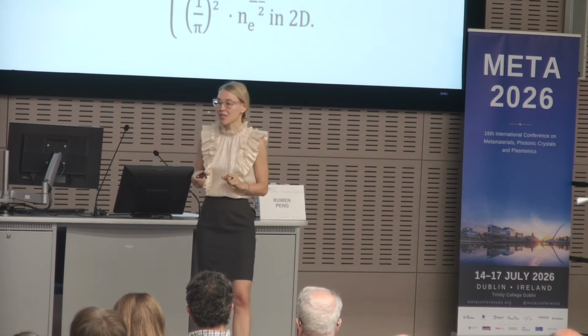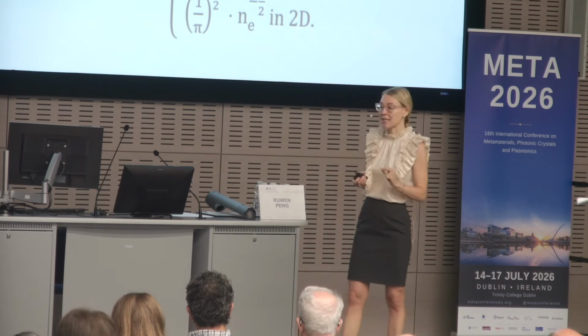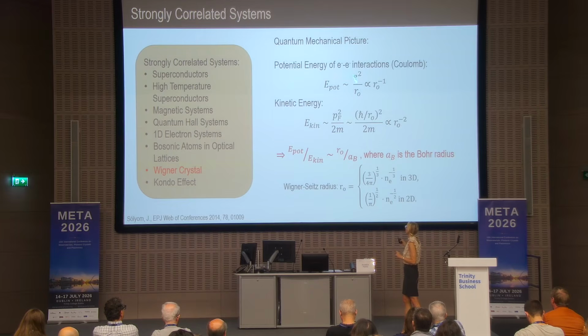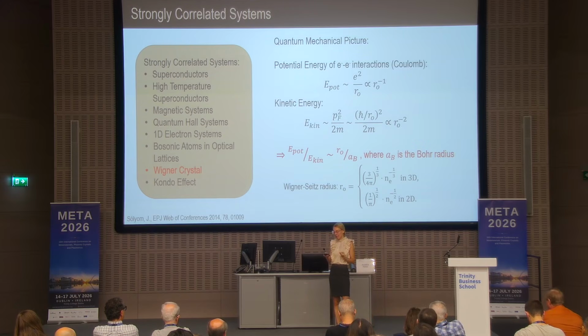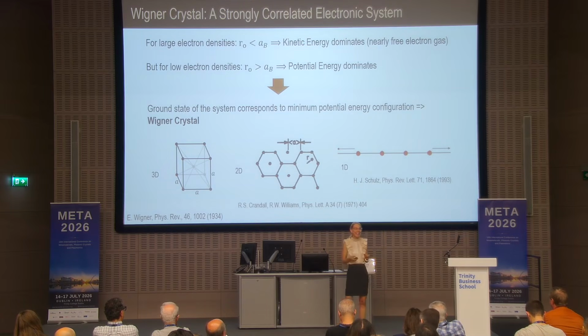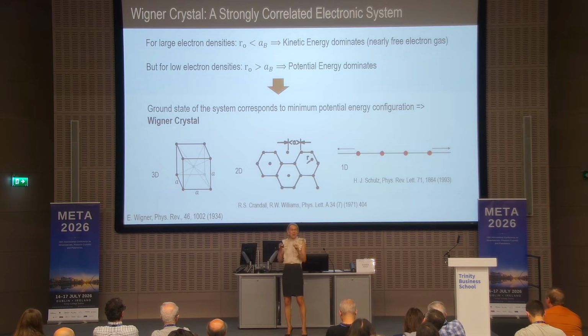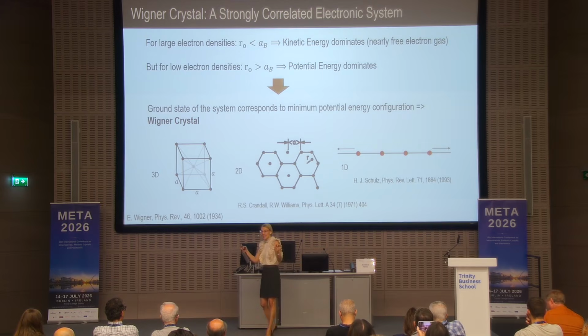If we look at the dependence of potential energy on the electron-electron spacing, it goes as 1 over r, so it's just Coulomb interaction, and the kinetic energy is connected to your Fermi velocity, and it actually goes like 1 over r squared. So if you are changing the inter-electron spacing, or if you are changing the density, it means that you are changing and playing around with the ratio of potential to kinetic energy. And playing around with this ratio means that you can enter the regime where your potential energy outweighs kinetic energy, even though you have electrons that are free to move to start with. They actually freeze into the lattice, which would correspond to one of the ground states of the system that's called a Wigner crystal.